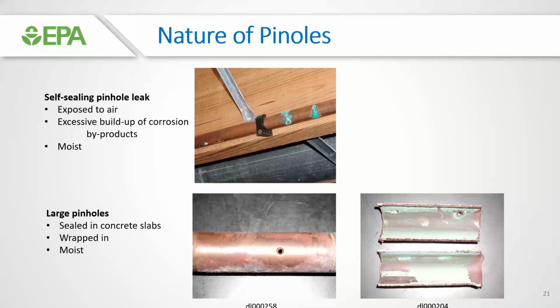Just wanted to show you the nature of pinhole leaks. Interestingly enough, a lot of pinhole leaks kind of seal themselves from the outside. You get this coating on the pipe. It looks kind of nasty, but you don't see the drips anymore. When do I see that? Well, I see that when the pipes are exposed to the air. But when you get something like this, when does that happen? Well, that often happens when the pipes are not exposed to the air. They're wrapped in insulation. Maybe they're under concrete slabs. Then you can run into these big issues that eventually spill out and become a big leak problem.